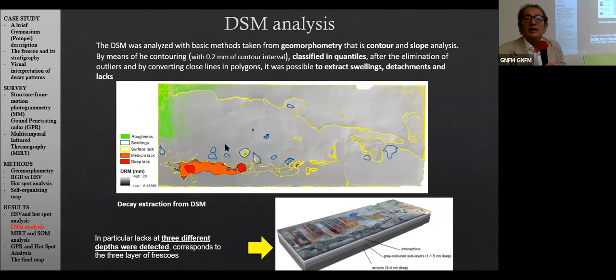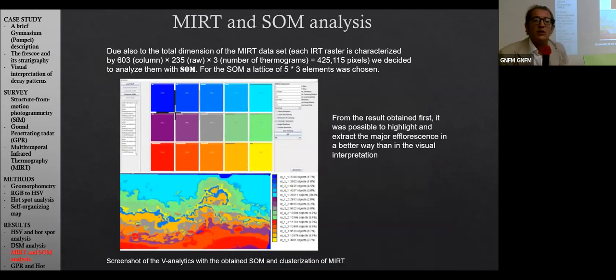As regards the DSM, with basic methods taken from geomorphometry, the data were classified in a number of quantiles, and so it was possible to extract swelling, detachment, and lesions in particular. Three different depths were detected, more or less corresponding to the 3 layers of a fresco. And finally, the SOM allowed us to identify, highlight, and extract with higher precision the efflorescence patterns, the efflorescence phenomenon.